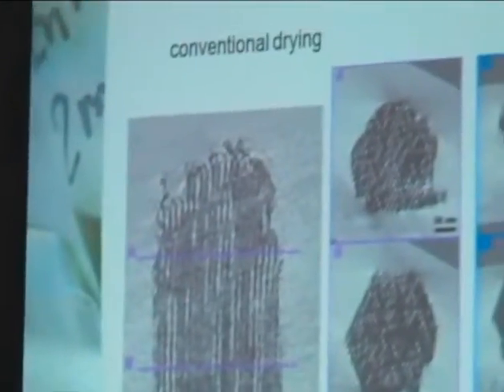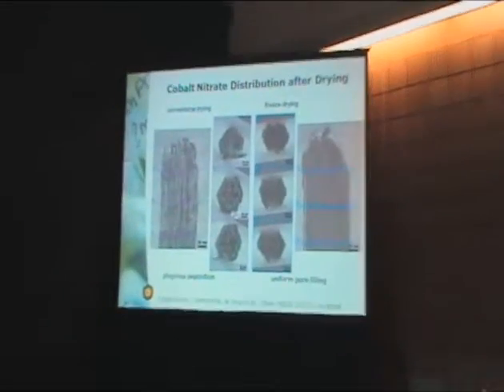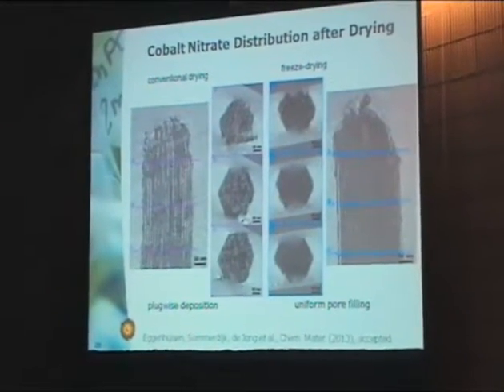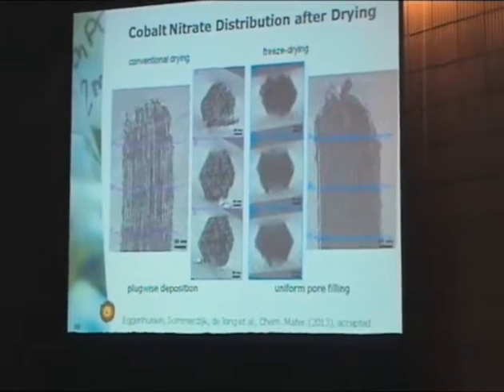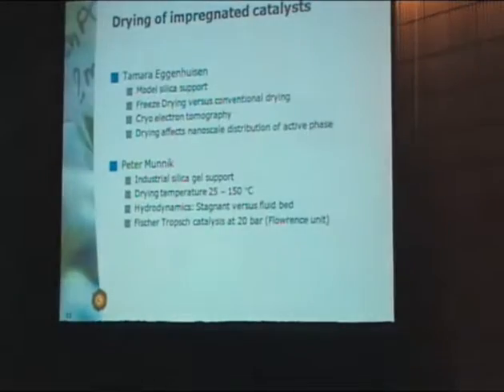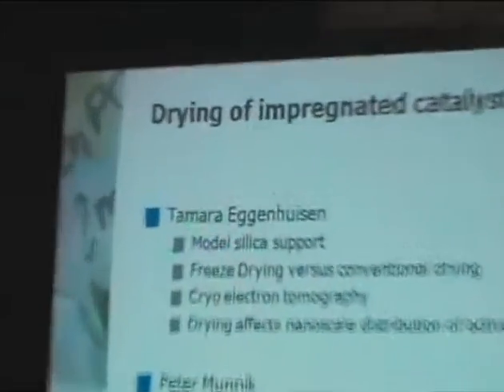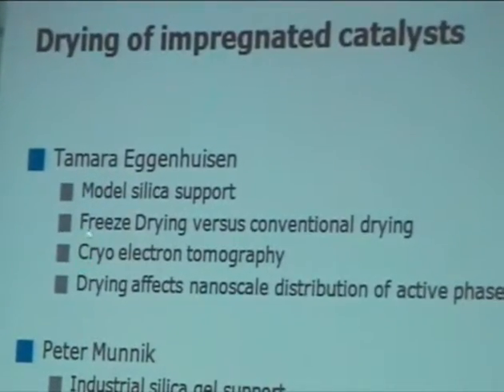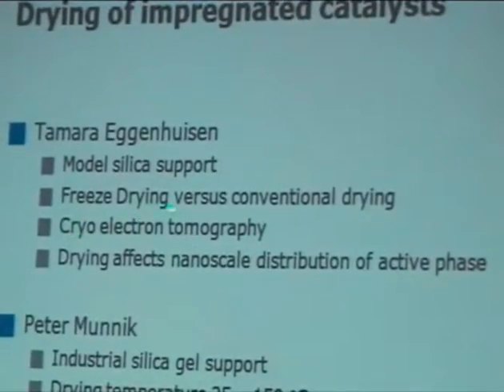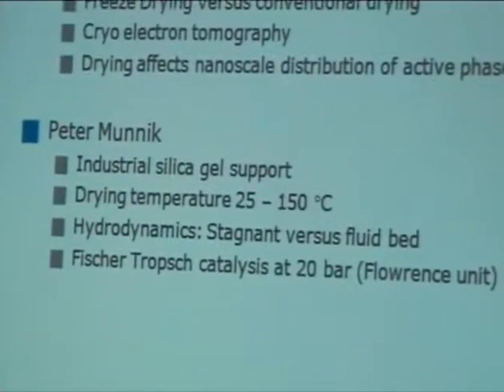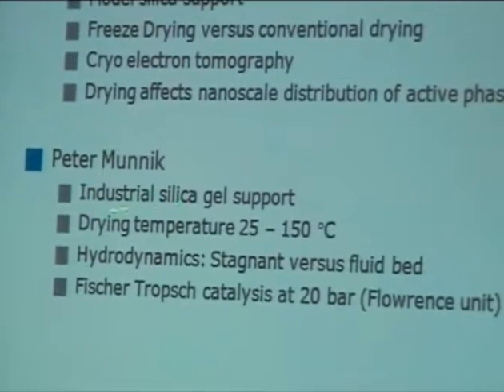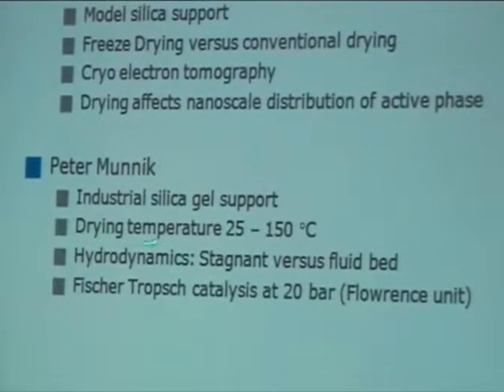If we carry out freeze drying, so we cool the sample to liquid nitrogen temperature, slowly heat it up, then we get a very uniform distribution of our cobalt nitrate. So clearly we can prevent the problem, but it's cumbersome, of course. Freeze drying is technically not so difficult, but it takes a long time. So what we did is that Tamara Eggenhuisen was working on this model support and used the freeze drying. Then another PhD student, Peter Munnik, started to work with the industrial silica gel support and vary the drying temperature,